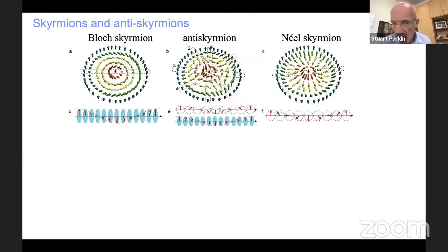That means the magnetization in the system, instead of pointing in one direction, breaks up into small magnetic nano elements in which the magnetization in each of these circular elements is pointing in the opposite direction. And therefore you have a circular boundary, a domain wall, and this domain wall is chiral, and it's also a Néel wall. It's very closely related to the Néel. This is a Bloch, in this case, a Bloch skyrmion.